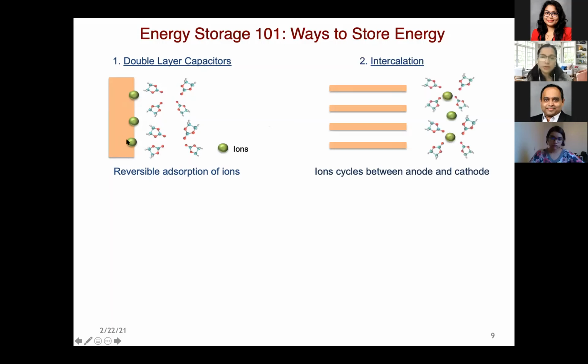If you want to utilize the bulk storage of the electrode, you can take a layered material and move ions into the lattice and push them. That's called intercalation. That's what we use in lithium-ion batteries. By utilizing this bulk storage, you can store a lot more charge. The cycle life, the number of times you can charge and discharge a battery, is also pretty high. But you can imagine that we still have limited lattice sites, and if you try to push more, volume can expand and other bad things can happen to this battery.